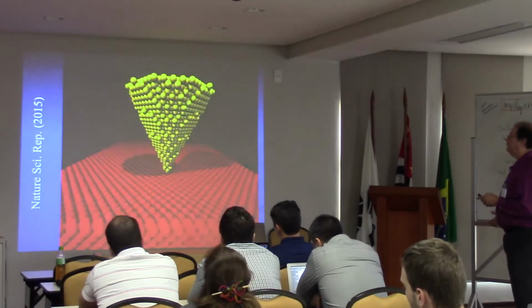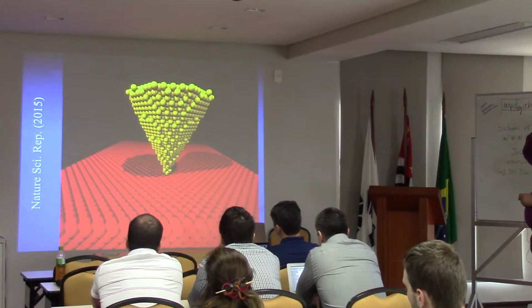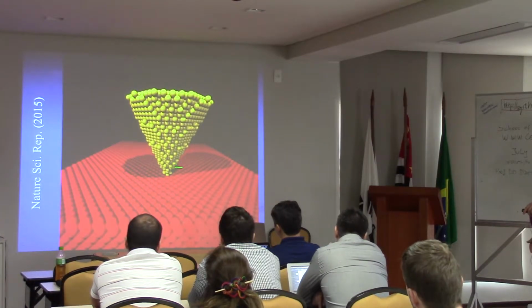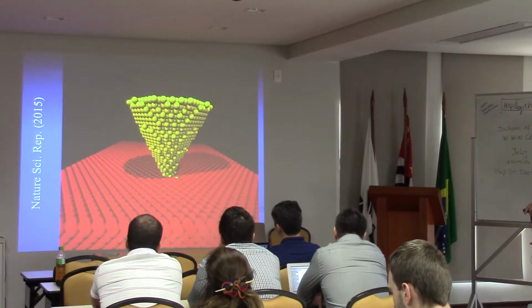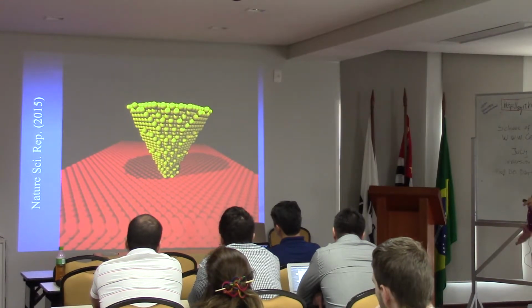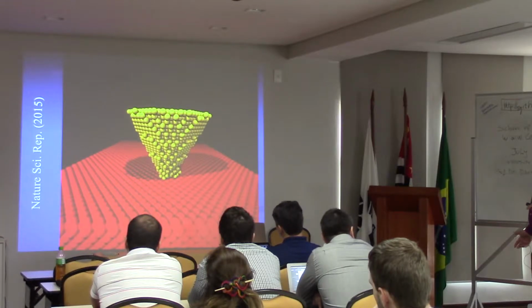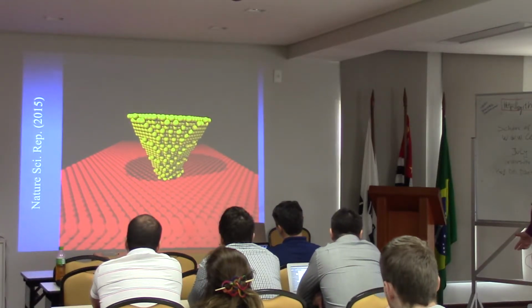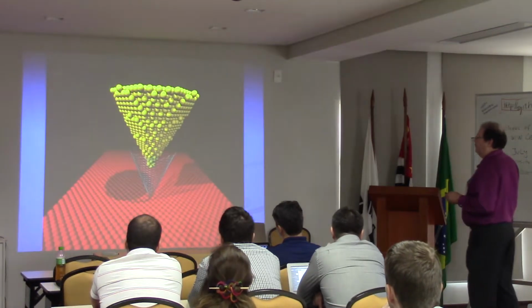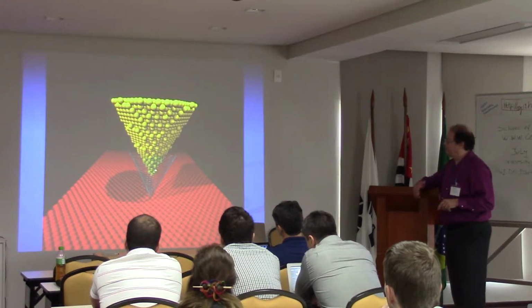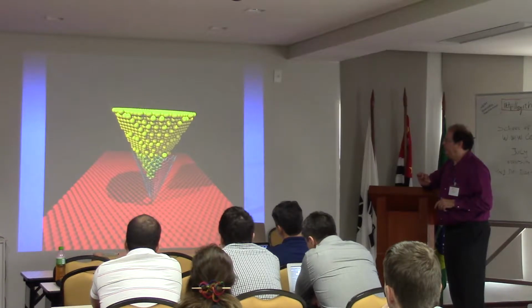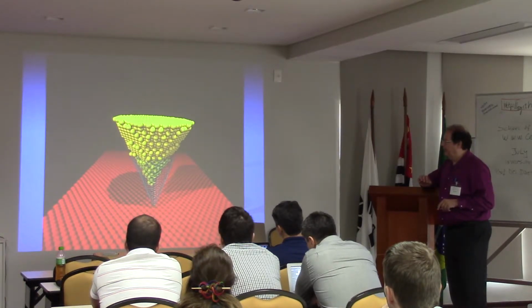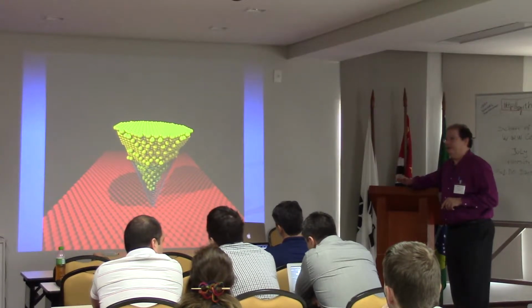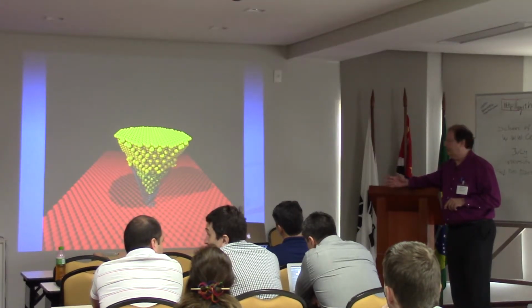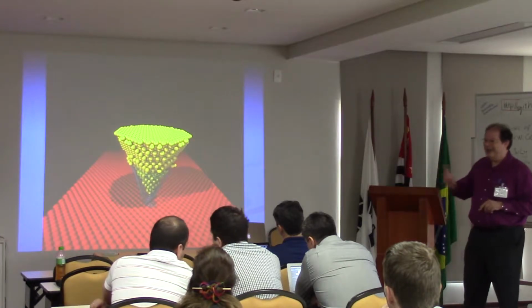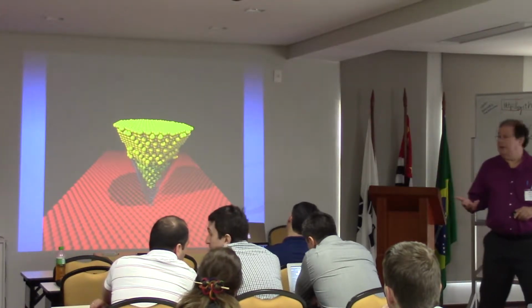So you run the simulation for this. See, this is the naked gold. You see, it's very easy to deform. Then if I retract the tip, it's almost a permanent deformation. You cannot use the tip anymore. But if you use the nanocone to encapsulate, you see a very interesting phenomenon. It not only protects the tip from direct contact with the substrate, but more important, and that is the secret why the tip becomes much better.